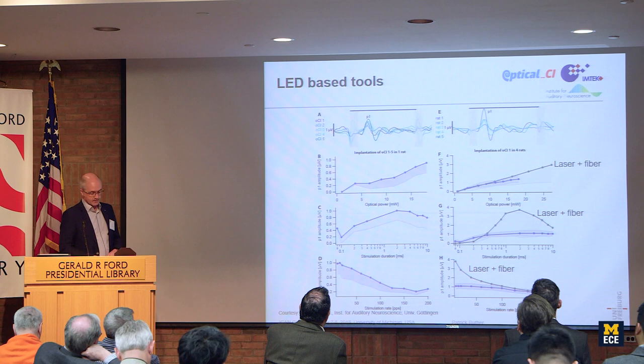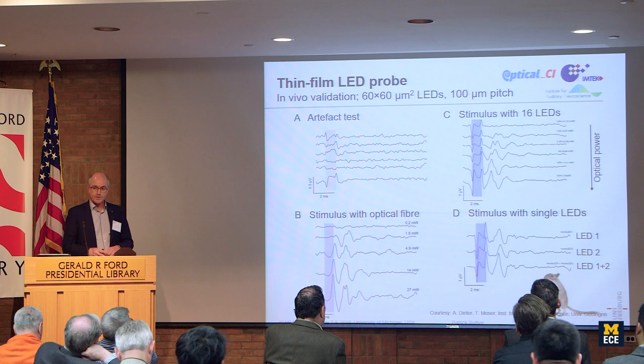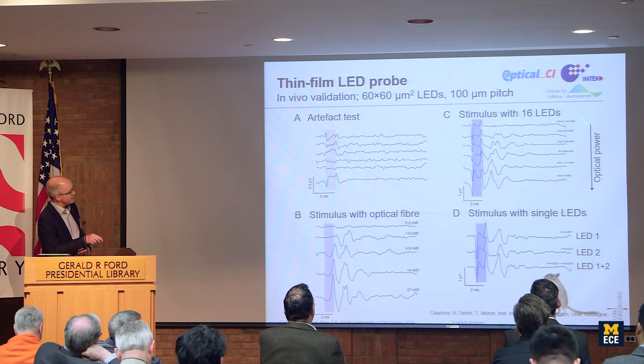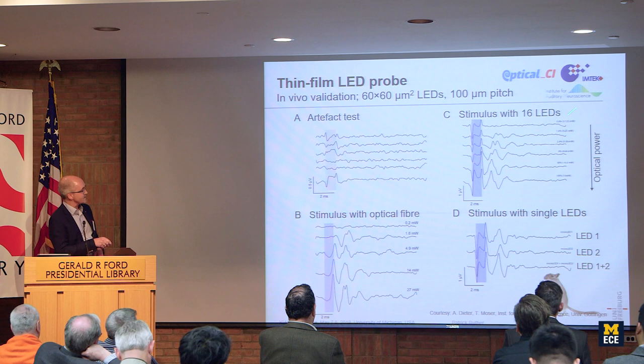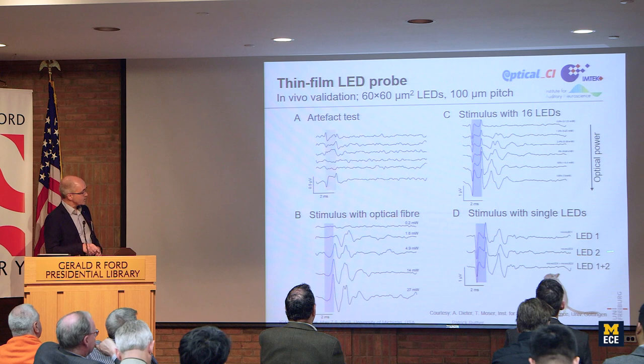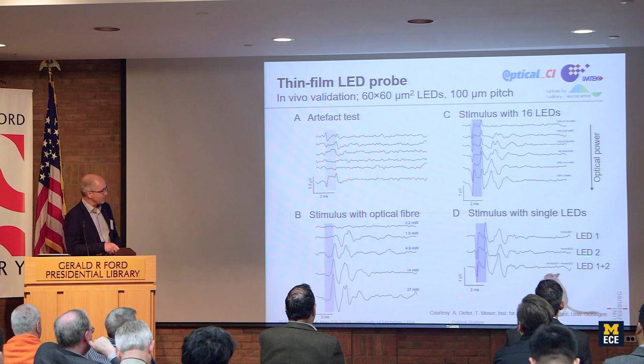So it's functional. The second good news here is that also those thin film LED probes of Eric are functional. So just in this panel, we see that when we implant the probe that in this case contained only 16 LEDs, we could again evoke brainstem responses, and we could also then discriminate between two LEDs. And of course, if you then stimulate both LEDs, you obtain a larger response.